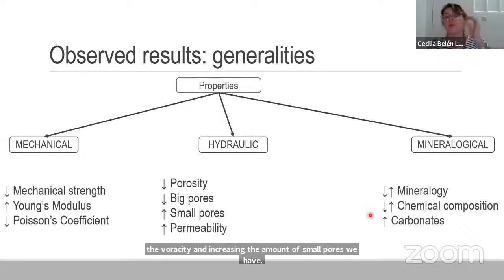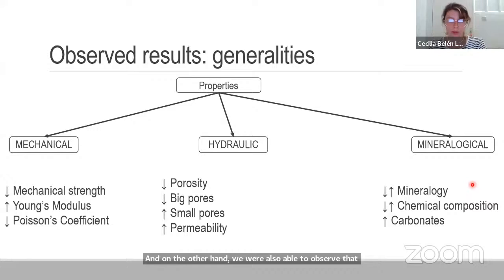On the other hand, we were also able to observe that this reaction between the CO2 and the plagioclase produced an increase in the carbonatic content.